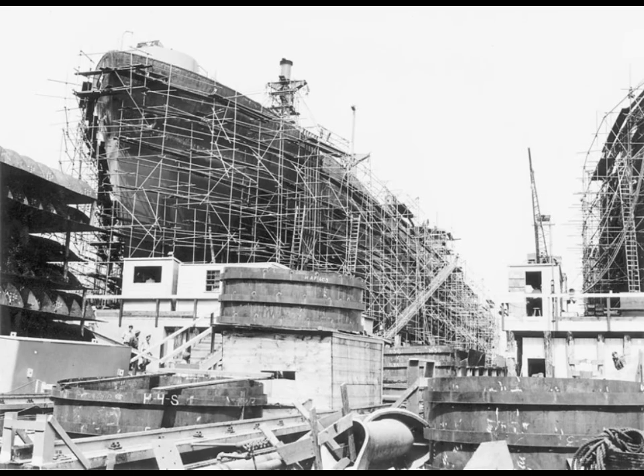The solution wasn't abandoning welding, it was better metallurgy and design. Steel composition changed to provide higher fracture toughness, especially at lower temperatures. Ships incorporated crack arresters, belts of different steel high on the sides that would stop crack propagation. Design eliminated rectangular corners that created stress concentration points. New welding techniques reduced internal flaws.